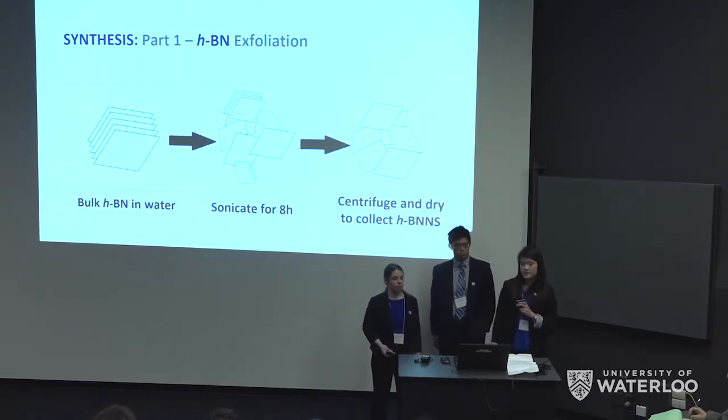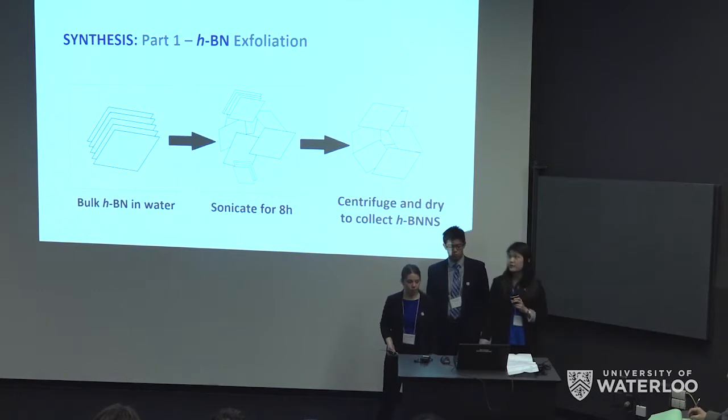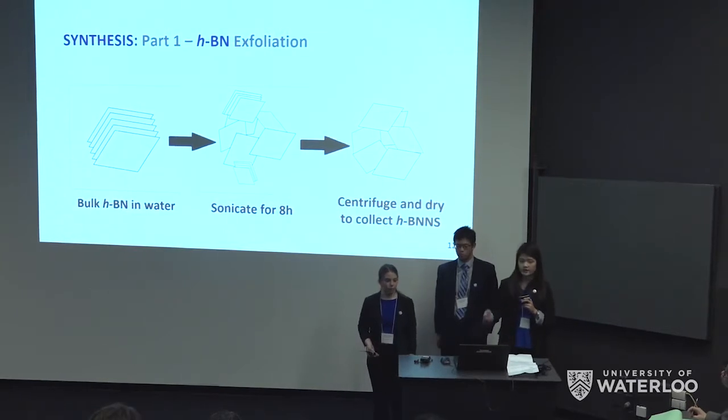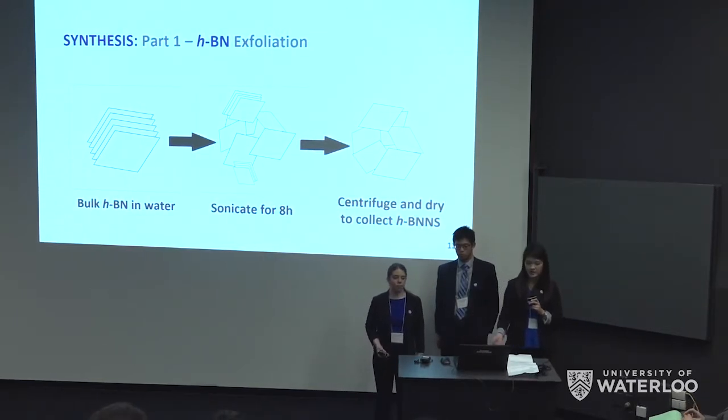Our synthesis consists of two parts. The first part is the exfoliation of bulk HBN. We disperse it in water, sonicate it, purify it through centrifugation, and collect it with freeze drying.